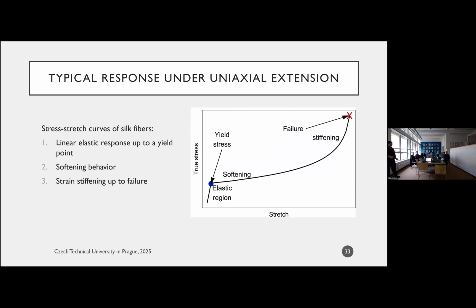And so it turns out that when you start stretching the fiber, you get what we call an elastic region or a linear region, right? So you stretch it initially, there's a linear regime. After the linear regime, it reaches some sort of a yield stress point, and after the yield stress, there's a plateau, there's like a softening effect. And then after the softening, there's the classical stiffening, right? So it stiffens. This very much resembles, it's very typical of glassy polymers. But I would argue that the mechanisms here are different than in glassy polymers. And so the question is, why is it that this is the trend that we're seeing, right? How do we understand this trend?